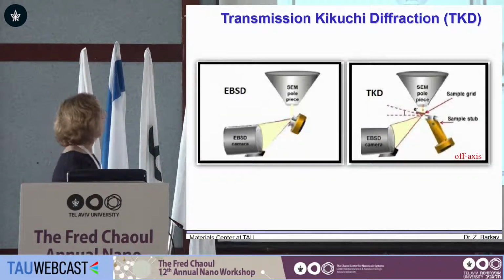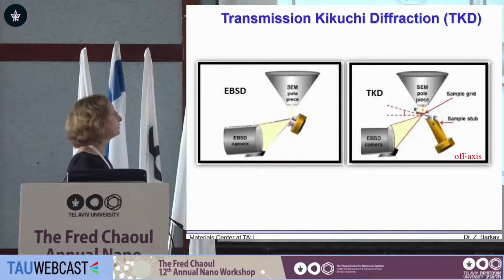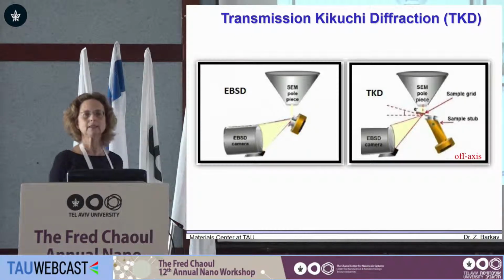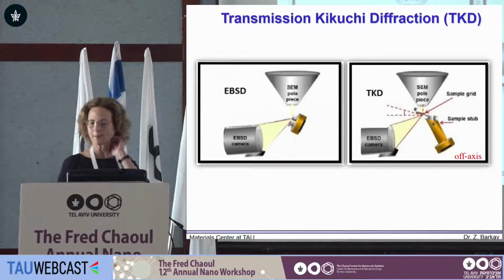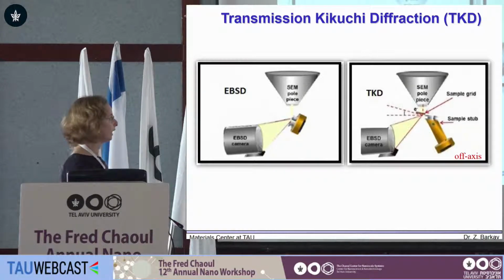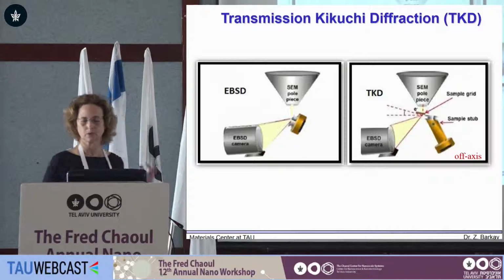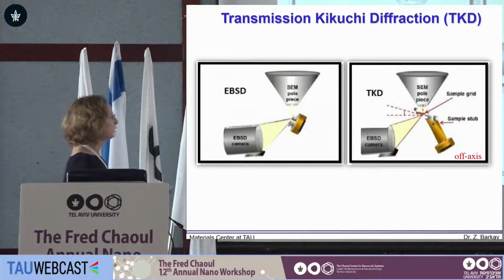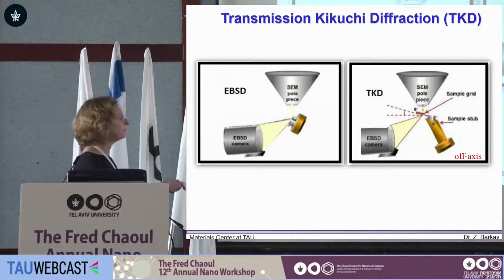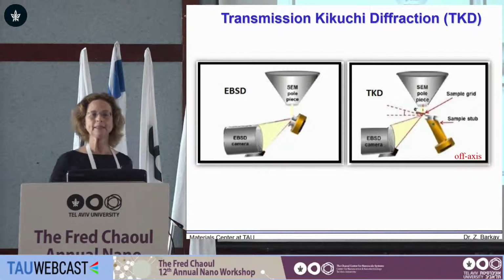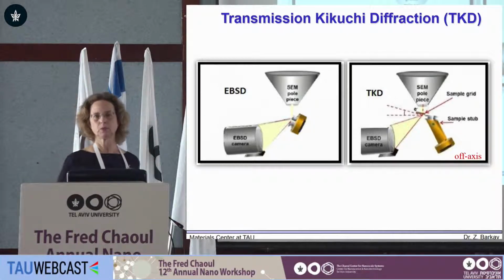So usually, as I said, we are getting information from bulk materials using reflected signal, and this signal could be signal for backscattering as well. Electron backscatter diffractions are specific electrons that contribute, and in this case the information comes from the upper surface of the material. But in case we tilt the sample 90 degrees to this direction, we can have transmission information in this off-axis configuration, and then we have Kikuchi information, called TKD, transmission Kikuchi diffraction, from the bottom surface of the material.